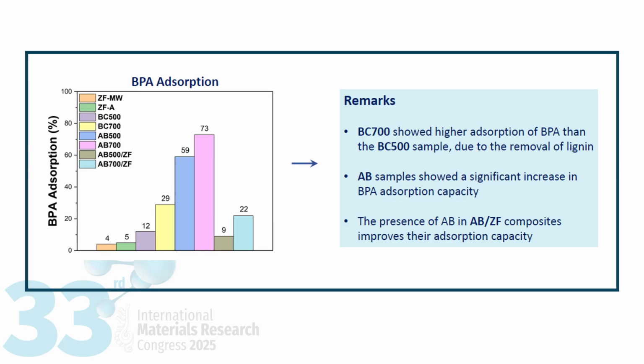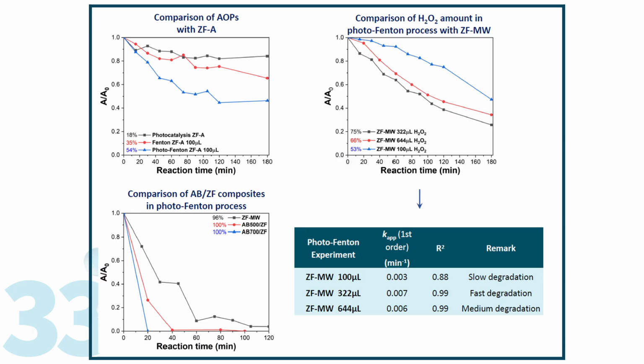BPA adsorption experiments. In the results of BPA adsorption, BC700 showed higher adsorption than the BC500 sample due to the removal of lignin. AB samples showed a significant increase in BPA adsorption capacity. Moreover, the presence of AB in the composites improved their adsorption capacity. In the experiments with different advanced oxidation processes with the ZF-MW sample, it was observed that the Photo-Fenton process showed greater BPA degradation compared to photocatalysis and the Fenton reaction.